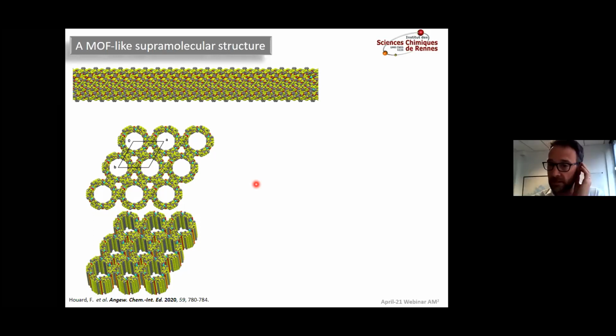No, because you have immediate dissipation into your solution, and you see the overall temperature that we are measuring is quite low. We have a plateau at 56 degrees, so we don't have a global high temperature. This is very localized, at least at the power that we are using. You can use transducers to make very high ultrasonication, and maybe it should be different. But on this kind of average power sonication, we don't see any damage on the samples.